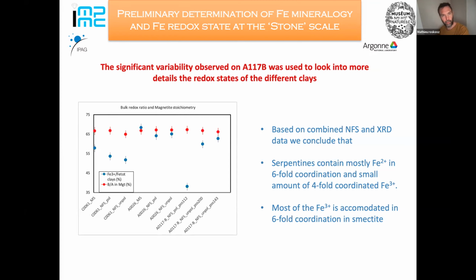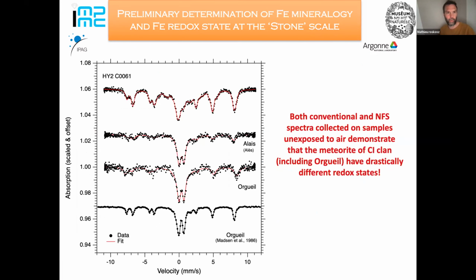Once again, all this data were collected without any exposure to air. Now, of course, what you want to do when you get this kind of samples straight from space is to compare them to the materials that we have on Earth in our meteorite collections, and that look very close to these materials. And so it was found that geochemically speaking, Ryugu is very close to the meteorites Orgueil and Ivuna, so it's a CI chondrite.